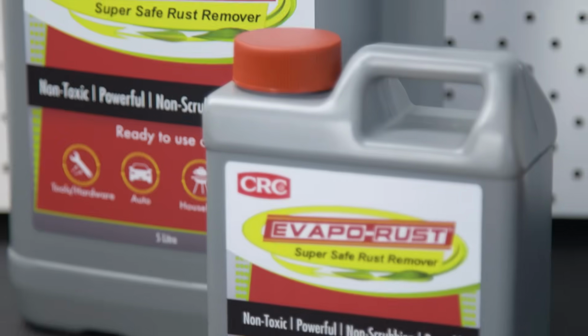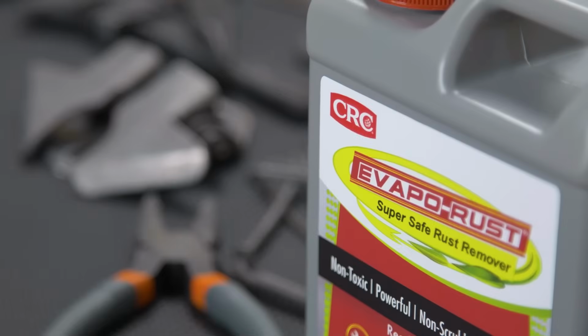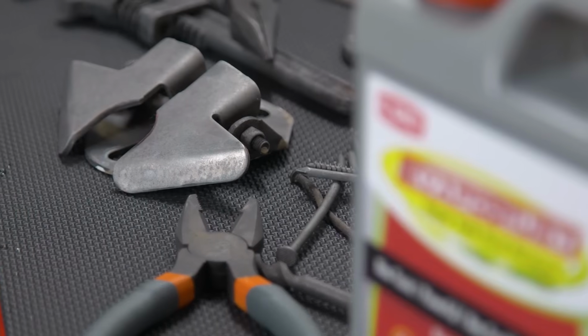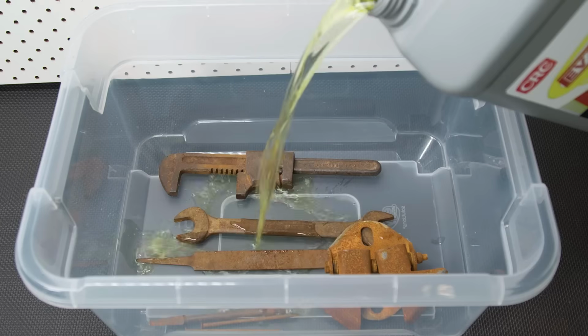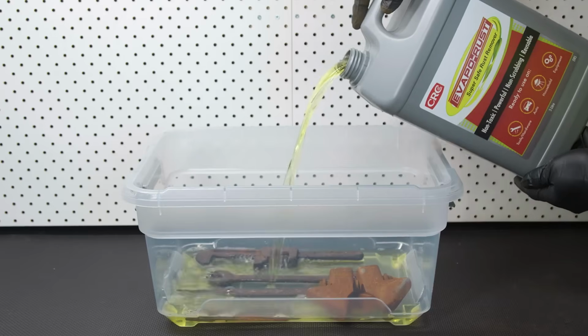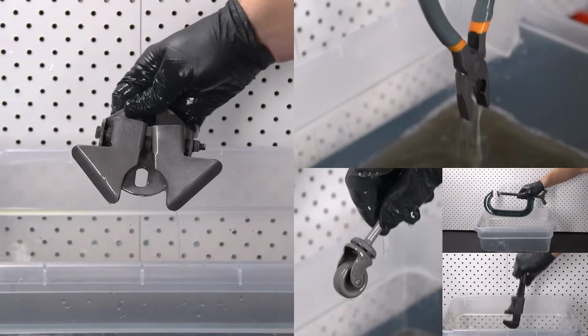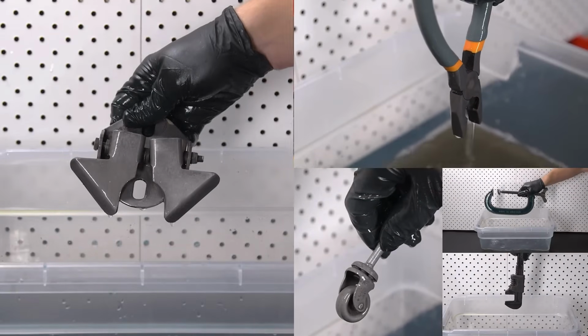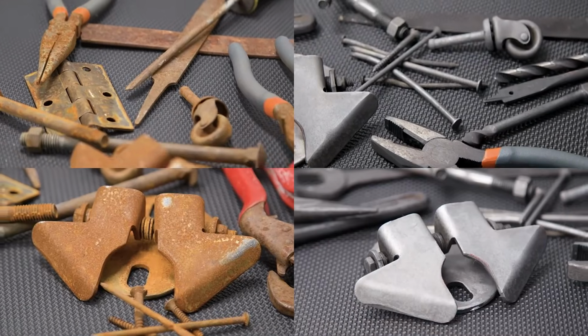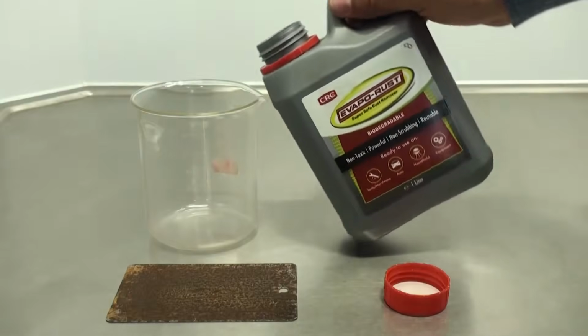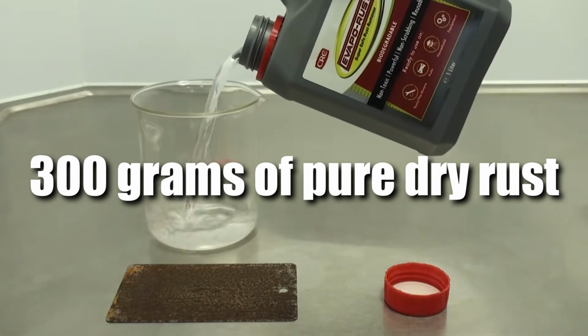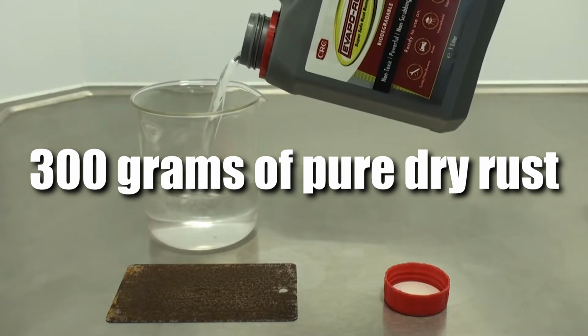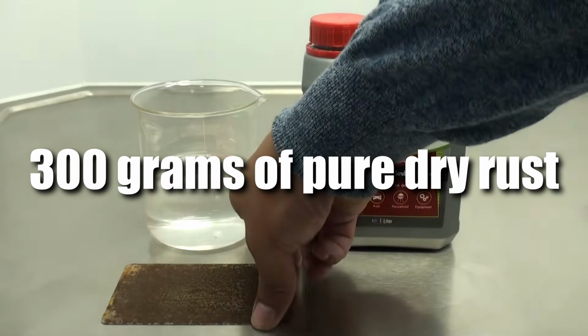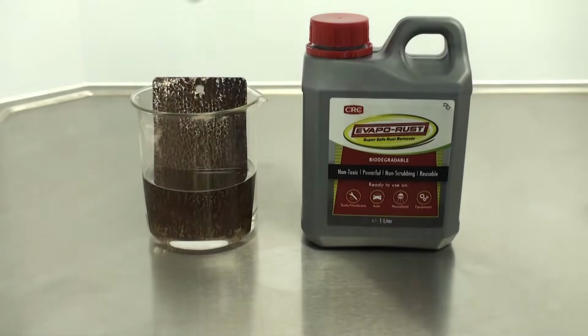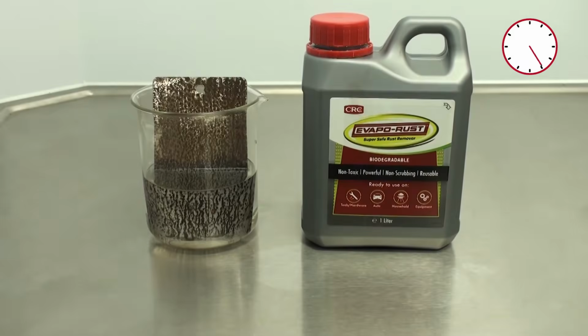Use a chelating agent. Products like Evapo-Rust operate at near neutral pH. The active molecule selectively binds to the iron ions inside the rust structure and strips it away, without generating a single free hydrogen ion. The base steel is completely unaffected. 1 liter of Evapo-Rust can process approximately 300 grams of pure dry rust. It is non-hazardous, it is reusable, and it will not destroy the metallurgical integrity of a tool that took decades to build.